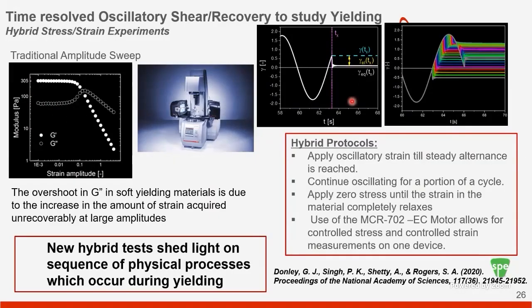This novel experimental protocol, published in PNAS a couple of years back, shows a unique approach combining strain-controlled oscillatory shear with stress-controlled recovery tests. This technique provides decomposition of recoverable and unrecoverable strains, allowing you to understand the solid-like and liquid-like contributions to the yielding process, giving a much better sense of how to characterize yielding in a time-resolved manner.